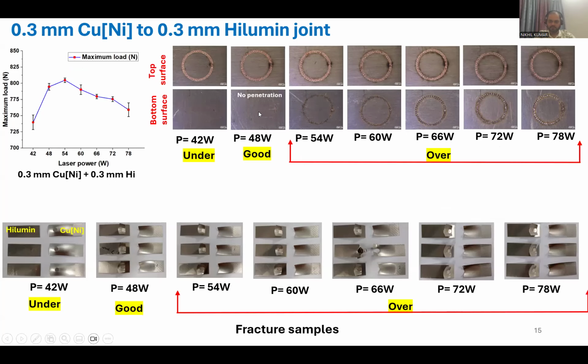The people doing the nickel plating on the bare copper to avoid that kind of damage, the oxidation or any bare environment. So here there is a 4 micron or 3 micron nickel coating on the bare copper. And a similar concept here is used to identify the good weld. The first example is breaking from the top sheet, and the other example is there is no penetration on the bottom sheet. So here also we are getting very good strength because nickel is making it compatible, helping in welding with the laser, because nickel absorbs more energy as compared to the bare copper.